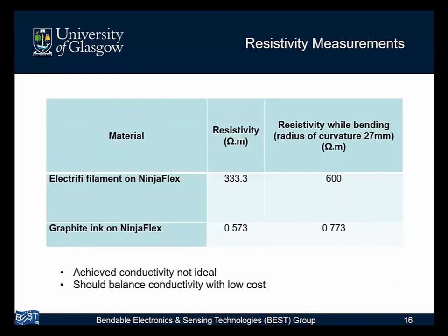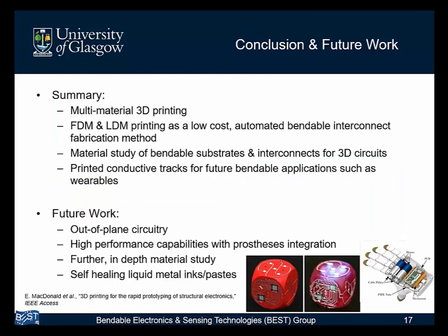The graphite ink itself shows a much lower resistivity than the filament. However, it's still, I think, quite high in terms of high-performance connectors for 3D circuits. And in that, I think it's clear it's not a very comprehensive study. However, with the fact that this area has not really been explored before in terms of bendable interconnects for 3D circuits, we're quite excited to look at this further, particularly with the optical measurements of these materials.